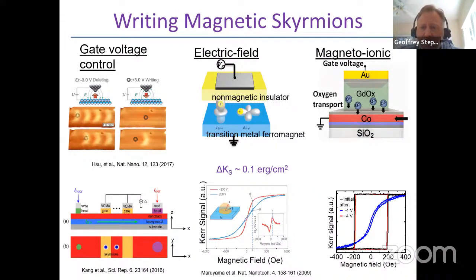And what we found is that ferrimagnets are a beautiful host to use ionic control to control individually the sublattices and allow for local electric field writing of spin textures. So we showed some number of years ago, using a gate oxide in which the gate oxide is not a passive oxide but really an active oxide, that one can use a gate voltage to move oxygen towards or away from an interface and control perpendicular magnetic anisotropy in a thin cobalt film.